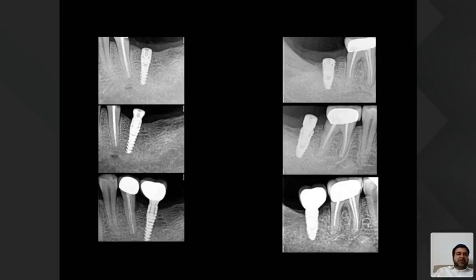In the middle, we have the case implant in stage 2, while on the right we have the control implant following stage 2. And the bottommost picture is that of 1 year post-loading. Now you can see how beautifully the crestal bone is still preserved post-loading. Of course, near the control we can see a slight amount of resorption, but it's quite within the acceptable range.